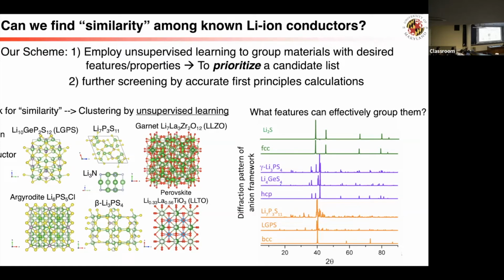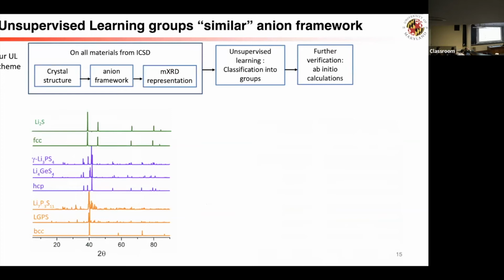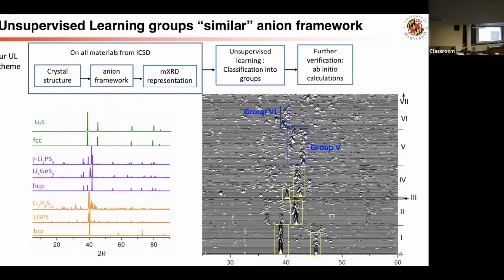So with that, we can perform this unsupervised learning, and we did it on all lithium ion containing materials. We just take the anion framework, that is the XRD pattern generated by computer, and then do unsupervised learning to cluster them together. You can see this data looks like each line is a diffraction pattern, but basically you see they're organizing into a few groups.